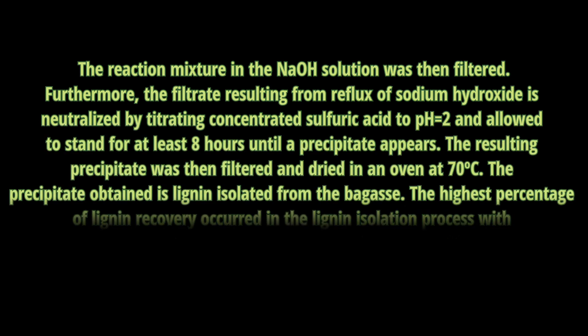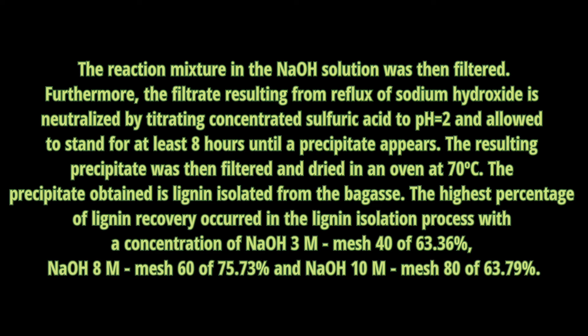The reaction mixture in the sodium hydroxide solution was then filtered. The filtrate resulting from the reflux with sodium hydroxide is neutralized by adding concentrated sulfuric acid to pH 2 and allowed to stand for at least 8 hours until a precipitate appears. The resulting precipitate was then filtered and dried in an oven at 70 degrees Celsius. The precipitate obtained is lignin isolated from the bagasse.